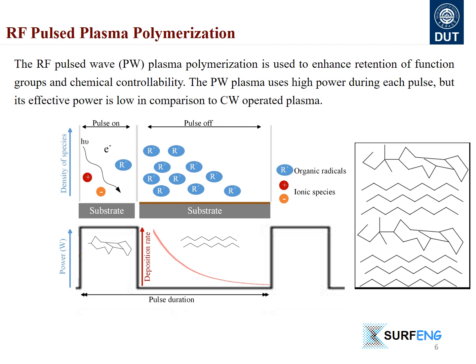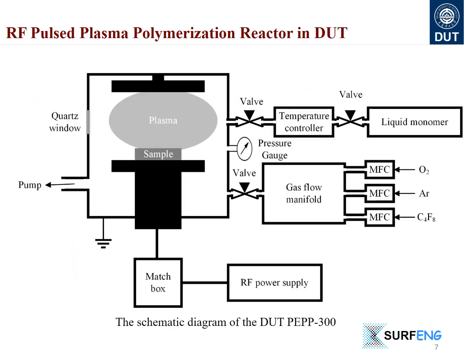In this technique, the RF power is applied for a specific time, pulse on, and during this period, reactive ions and neutrals are produced. Since ions have a shorter lifetime, a greater selectivity of neutrals during pulse off reduces the coating damage from reactive ions etching. The reactor was equipped with continuous and pulsed RF plasma generator, which was connected to automatic matching unit.